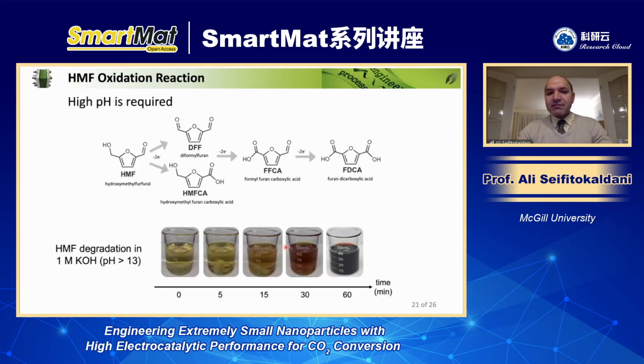The problem is whenever we use metallic compounds, we need to work in alkaline environment. Otherwise, the HMF doesn't get activated, and then the reaction selectivity and activity is not great. So you have to work with alkaline electrolytes such as 1 molar KOH to initiate the reaction. And these days, you see a lot of papers for the HMF utilizing 1 molar KOH, for example. But most of them don't even discuss that.